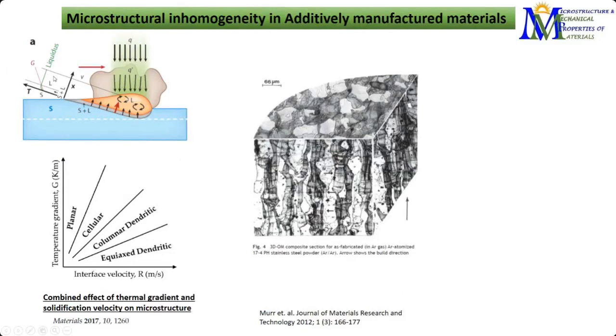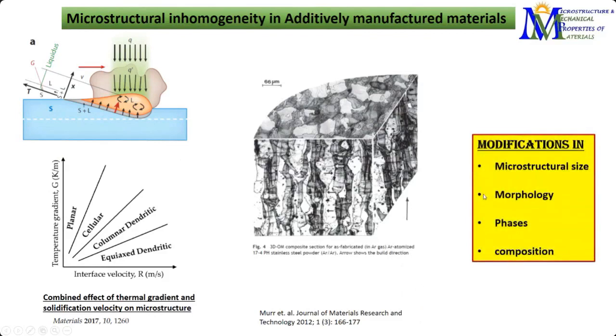What we have there is a difference in the melt, cool, and heat distribution, as I said, and that leads to variation in the microstructure within the same structure itself. So you can see this is a 3D view, and we can actually figure out the layers, each of these layers, from the structure itself. We have equiaxed structure, dendritic structure - first you can see big dendritic phases, and then equiaxed, columnar, all different kinds of morphologies.